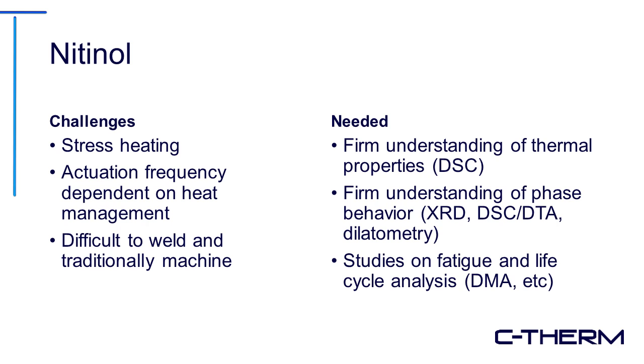DTA is usually the best if you're looking for the onset temperature. With DSC, you can pull the data out as well. It's just not going to be quite as sensitive to the onset temperature. And dilatometry lets you look at coefficient of thermal expansion, and some phase changes are visualizable on dilatometry if the phase change is associated with a change in the CTE of the material. And then finally, you need to understand what the fatigue behavior and the life cycle is going to look like for the material. So most often, people are going to be using a technique called DMA, or dynamic mechanical analysis, to achieve that one.